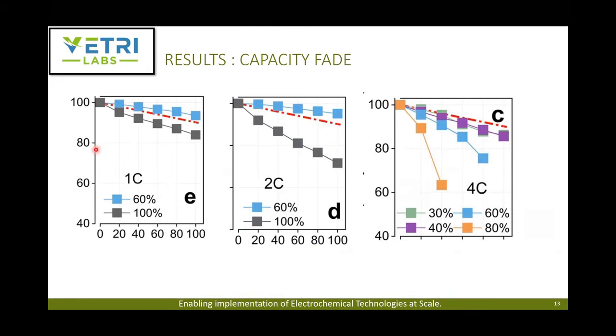What's plotted here is the capacity fade. So you started with 100% capacity, and as a function of your partial cycles, how did the capacity fade, and what's the relationship, whether it's linear or nonlinear. And this red line here is a very slow charge. It's a 0.5 C type discharge. This is being used as a reference point to compare how the performance is when you're doing it at high rate. Okay, so 100 cycles at 0.5 C is that red line.